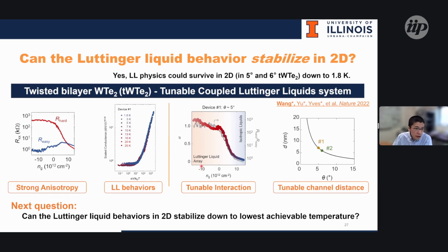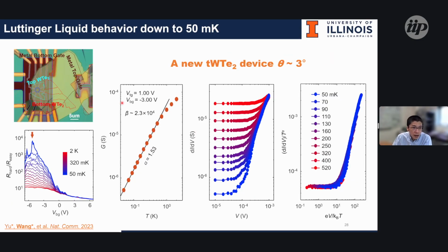The next question is whether we can stabilize such Luttinger liquid behavior down to the lowest achievable temperature in our environment. The answer is yes. We pushed down to 50 millikelvin electron temperature, which is the reliable temperature we can trust in the lab, and we can still see good scaling of the power law with tunable interactions across a huge range of temperatures.